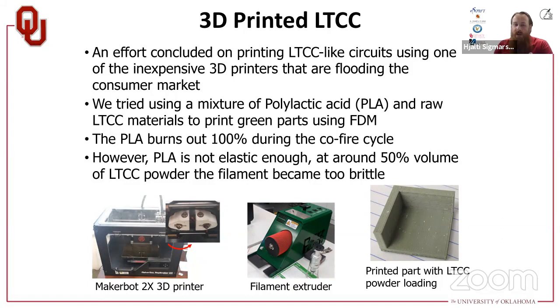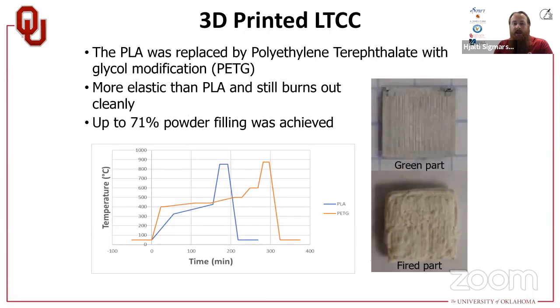First off, we started with our typical polylactic acid, or PLA, and the problem with that was that it was just too brittle. We couldn't get high enough ceramic loading into our plastic parts where we could burn out the PLA and be left with a good enough ceramic matrix that would sinter and not just fracture and turn into dust, so to speak. So we moved away from the PLA and went to PETG, which is way more elastic than the PLA, and we were able to achieve some 71% filling of this Heraeus X200 powder into a filament. We were able to use a MakerBot printer to print a part and fire it and get some nice parts out of it.